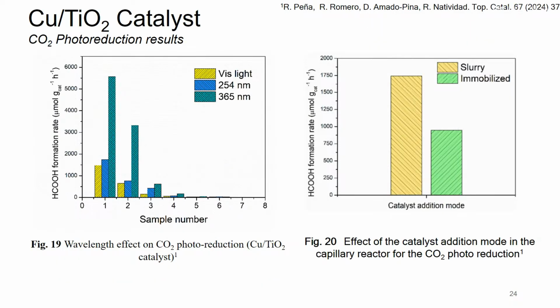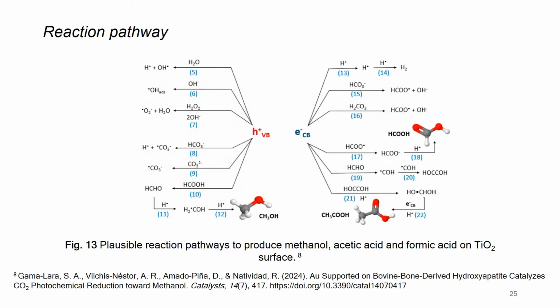This was the proof that it works with visible light. Here, the catalyst was immobilized onto the capillary walls, and here it was in powder. So you can observe the production, but it's still better with slurry catalyst. Here is the reaction pathway that we postulated with that study.